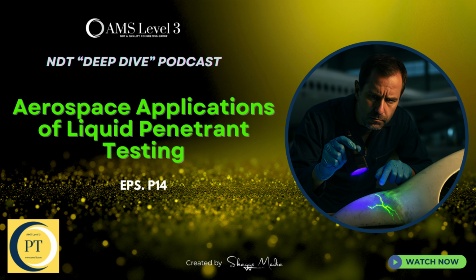And if they try to switch between fluorescent and visible dye penetrants, they face a serious contamination risk. A very serious risk. If a visible dye penetrant was used first, there's no guarantee all of it was removed. And if any of that visible dye residue remains, it will quench the fluorescence of the next penetrant, rendering the reinspection useless. Let's turn now to the highest stress, most exotic applications possible.